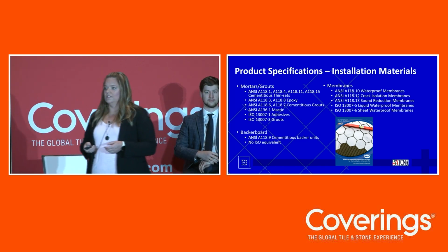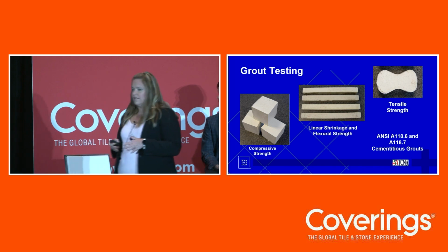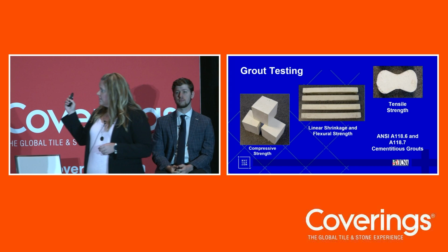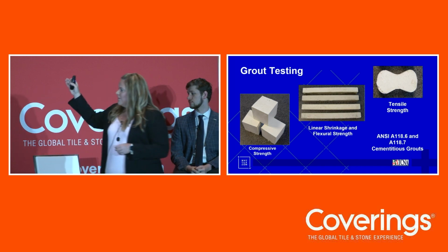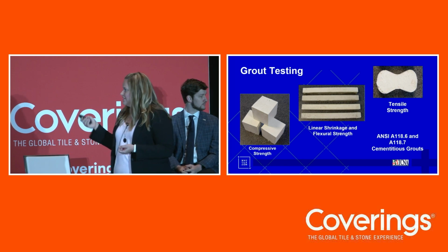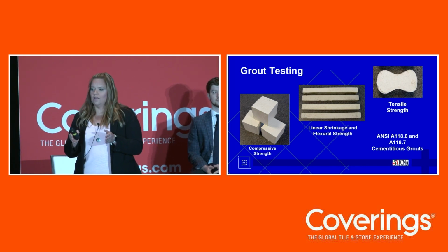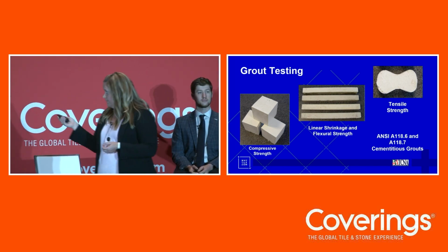So the testing that we're doing is mostly in ANSI standards in our lab. To show some of that testing, because there's a whole lot in there that I won't be able to get into, for grout testing, there are tests like compressive strength, linear shrinkage and flexural strength, and tensile strength. These are just pictures of the samples that we create with the grout. On the compressive strength, we just crush that cube, apply pressure until it breaks. For linear shrinkage, we're measuring how much change in the length of that bar, and then after that, we put it in a 3-point loading fixture and break that. And then for the tensile strength, we have a grip that can pull that sample apart.